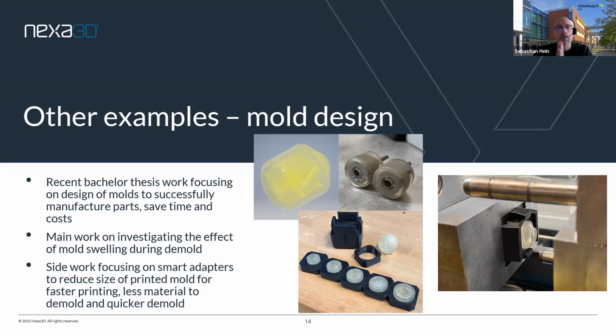One of the main takeaways that we realized was that this swelling of the mold itself is the issue that you have to look into, and you have to compensate it, but not just by avoiding it. So not just removing the outside part of the mold and just dissolving the inside, or the other way around, but you have to create the mold in a way that anything that swells and may induce a force on your part is counteracted by the other side of the mold. So you have to find a balance of the forces that can occur due to the swelling.